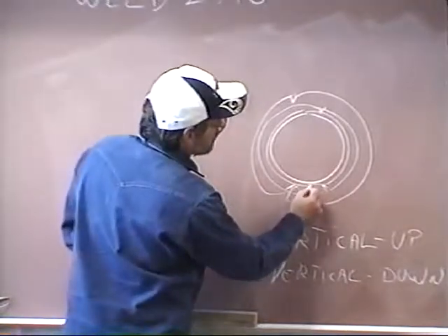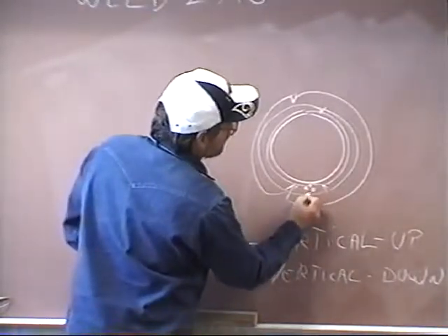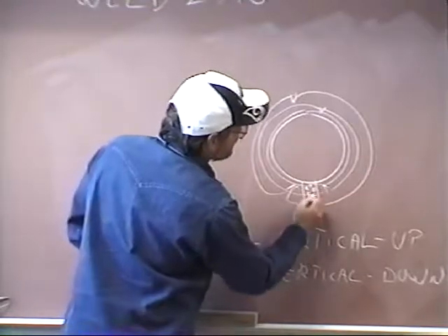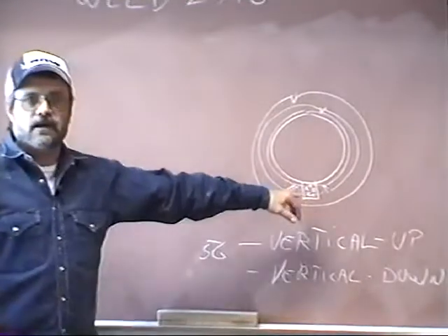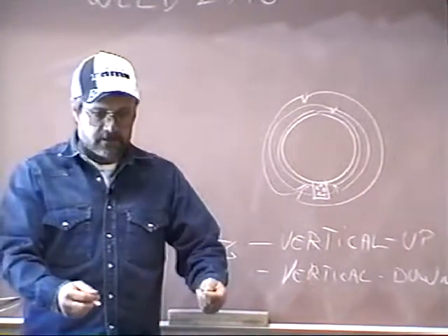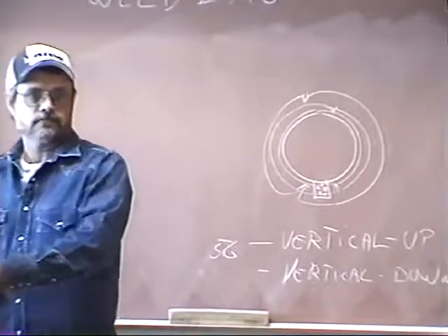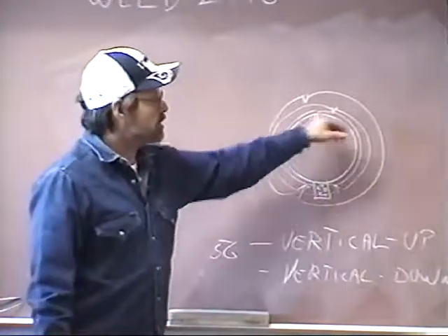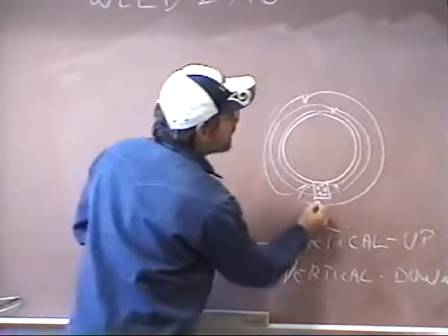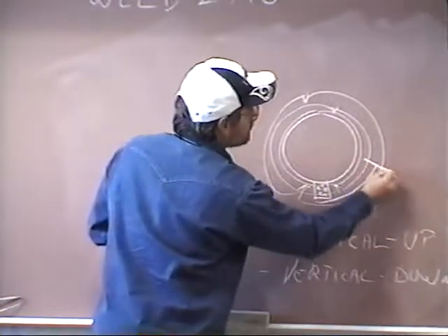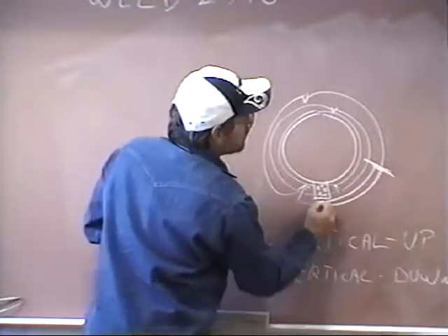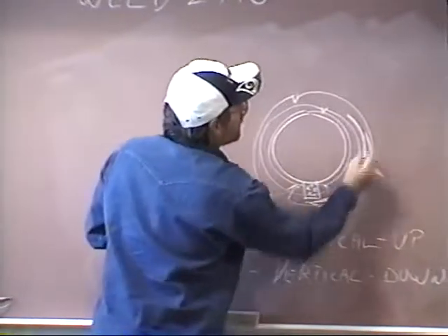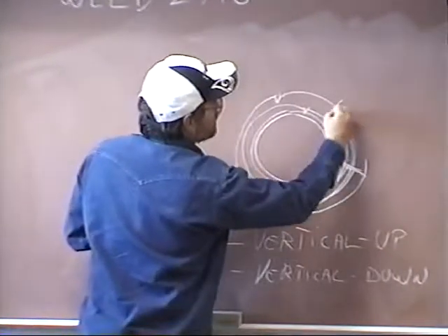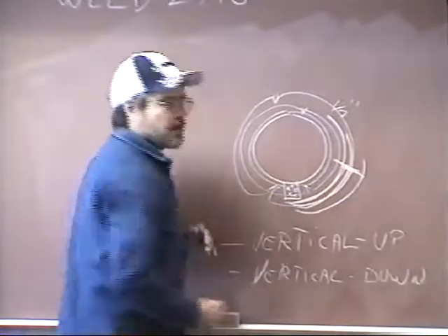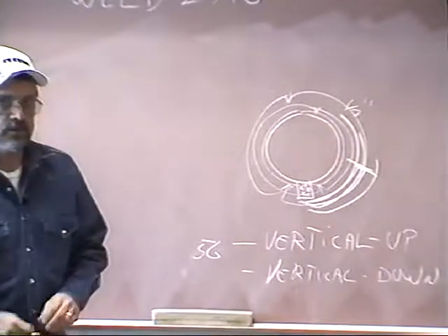But if you make all these starts and stops here in the same place, gosh, look at this. Now you've got such a concentration of defects that exceeds allowable limits. That's a rejection. So you want to make sure you stagger your starts and stops, and even coming up the side, don't stop at the same place every time. Take them a little bit further, and then back them up. So you want to have at least a half an inch between each start and stop, preferably more like an inch between each start and stop.